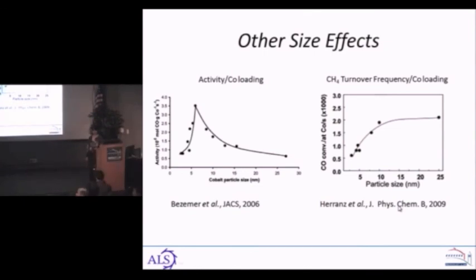So, to me, one of the most interesting topics you brought up was these two possible mechanisms of CO dissociating into atoms or CO inserting into a carbon chain that's already there. Do you have any ideas for experiments that might come next that could help you differentiate between which of those two mechanisms is really happening? Well, we think that this experiment helps show that the CO dissociation is happening, but maybe we could pre-adsorb methane on the surface and see if it still grows. If you produce oxygenated products, that would be a good indication of the second mechanism.